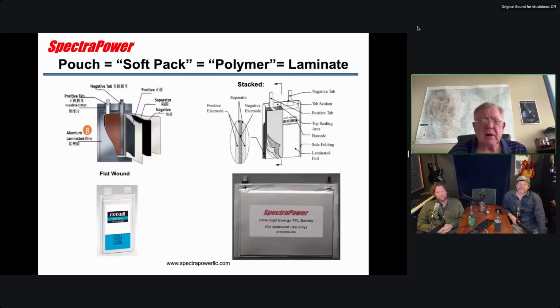And then finally there are what are called pouch cells. This is principally what we make here at SpectraPower, and you'll see a lot of different terminology: soft pack, polymer, which is kind of a misnomer, laminate. They can be made in two versions. One is a flat wound jelly roll, like a prismatic, or they can be stacked, where the electrodes are stacked one on top of another. Winding is faster, while stacking can give you a little bit better performance, but it's slower to do. So we make small quantities, and we use stacking. Is this what they use in tablets?